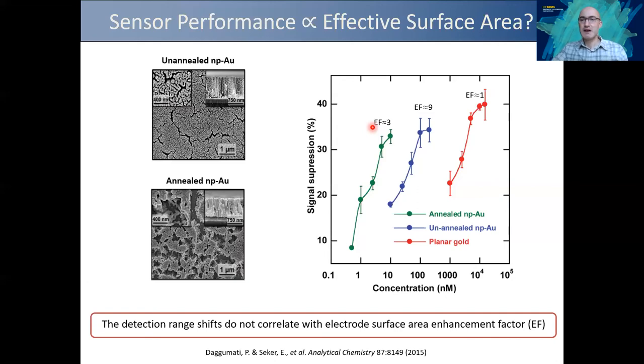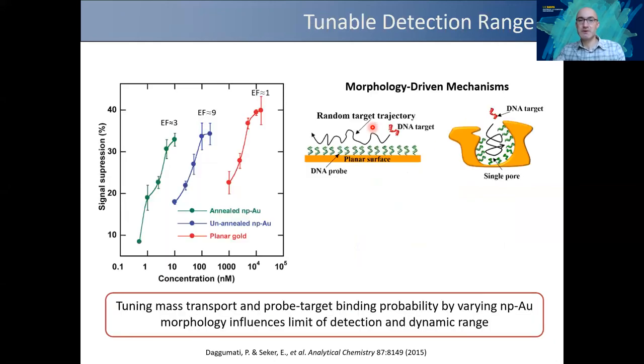So we wondered what the reason for this could be. We looked into this simple hypothesis: if you have a planar surface, just to compare the limit of detection difference between a planar surface and a porous surface, if a DNA target going through random Brownian motion approaches a surface and does not hybridize, it's lost into the bulk again. But if you have a porous surface, and the target goes into that porous structure, it's surrounded with so many probe capture molecules that it has a higher probability of being captured and hybridized, hence producing a signal. So we think that it's actually a transport mediated and also probability of capture mediated mechanism.